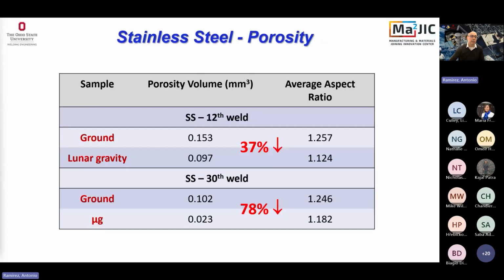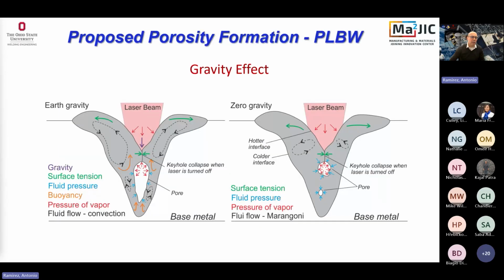Just to summarize, when we go from ground to lunar gravity, we had a reduction of almost 40% on the total volume of porosity. When we went from ground to microgravity, it's almost 80% reduction of porosity. Guess what? We don't really understand why this happened. And it actually just changed for other materials. So that's why these studies are needed. We have already some theories how this could be made.